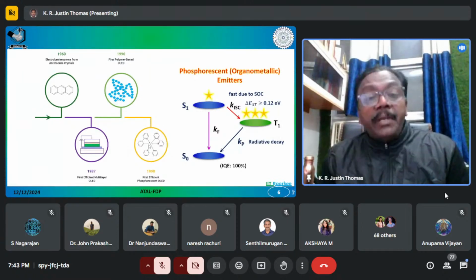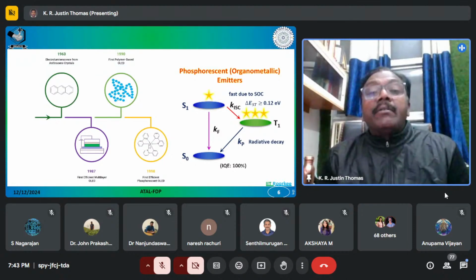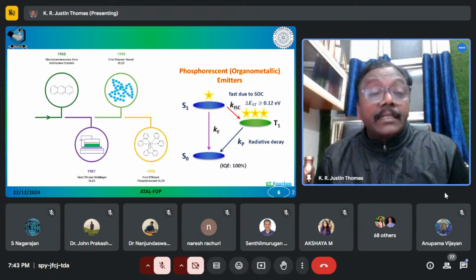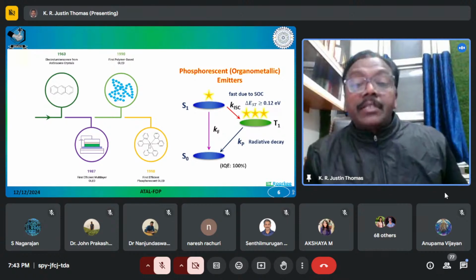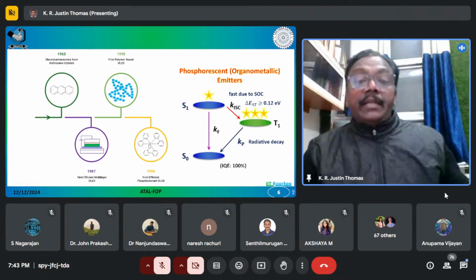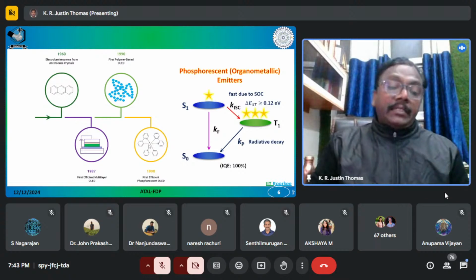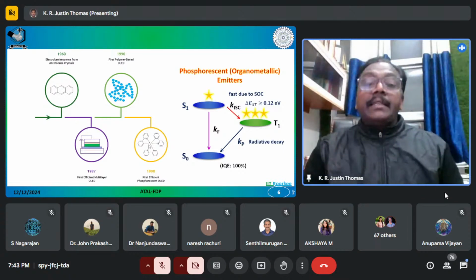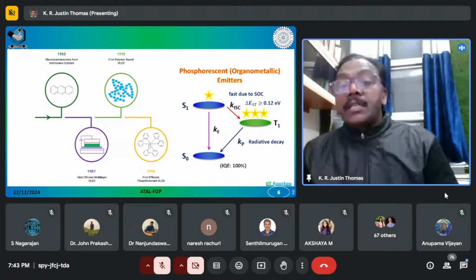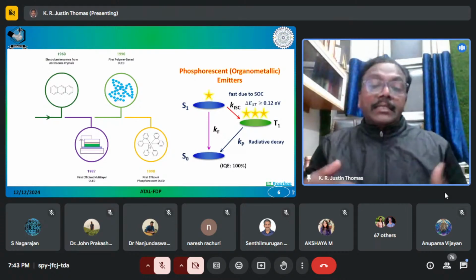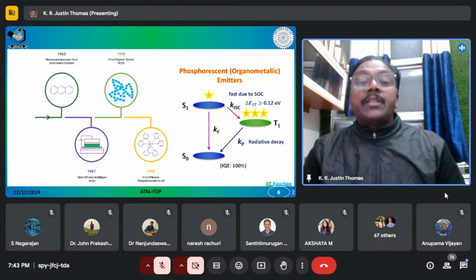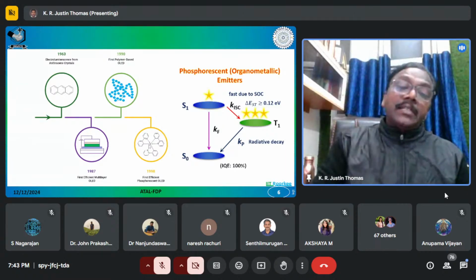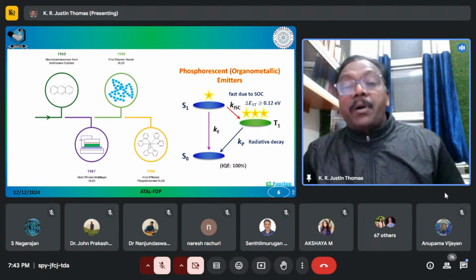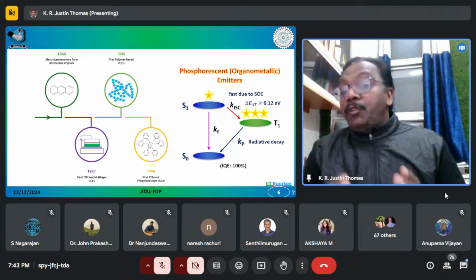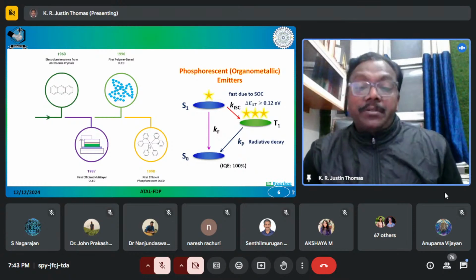However, because of the spin orbit coupling, they have a very fast intersystem crossing. The spin orbit coupling constant for these organometallic compounds is very high. So when there is an electrical excitation, you harvest singlet and triplet excitons, and these materials are capable of harvesting both. The triplet excitons relax to the ground state with phosphorescence, and singlet excitons undergo intersystem crossing and populate the triplet excited state. So you will have only phosphorescence from these materials.